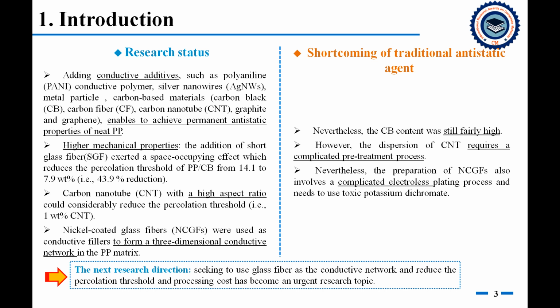Next, we review the research progress of antistatic composite materials. We found many conductive alternatives in fiber-reinforced polypropylene systems. Carbon black was used. However, this type of filler needs more content than carbon nanotube. However, the dispersion of nanotube requires a complicated pre-treatment process. Further, nickel-coated glass fiber was used as conductive filler to form a three-dimensional conductive network. However, this process involves some toxic material.